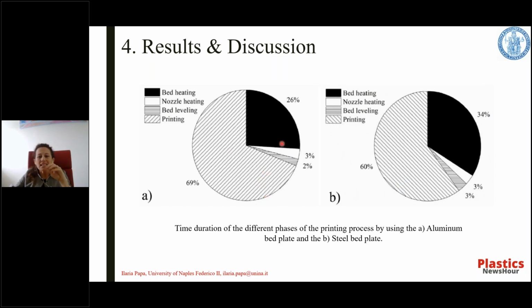Nevertheless, the printing time is independent from the capacity to reach and to keep the target temperature, because it depends just on the nozzle speed. So the significant differences reported in the energy spent are even more important, since it means that although the duration of each phase doesn't change, the energy spent is improved. The latter is due to the numerous on-off heating cycles during the printing phase that we have seen in the previous graphs, where we can see the signal go up and down. This phenomenon indicates that the 3D printer continuously requires energy to maintain the steel plate at 90 degrees, differently from the aluminum plate, according to their different thermal properties.